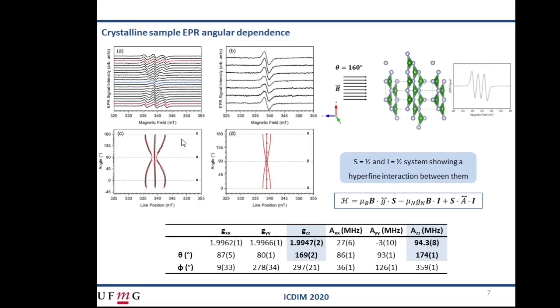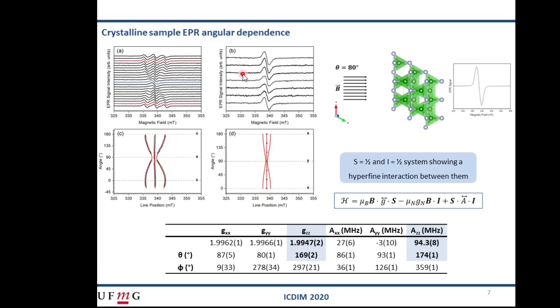In the case of hexagonal boron nitride, the nuclear spin may be associated with a nitrogen nucleus. Adjusting these line positions in these two figures of the EPR spectrum, represented here by these black points, we obtained these spin Hamiltonian parameters using this equation. And now we can describe how the electron and the nitrogen nuclei are interacting. The principal directions of the G tensor and hyperfine tensor are along the C axis.